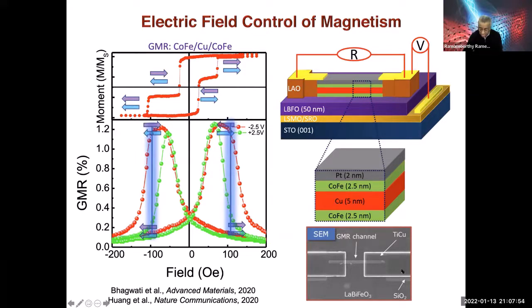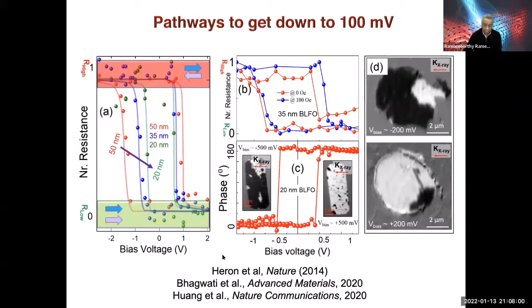Our colleagues at Intel fabricated 100 nanometer kind of devices. They all look essentially the same. The first challenge was how to go from 5 volts or 7 volts down to 100 millivolts. That's what Intel was asking for. So the first thing we did was to reduce the thickness. And this fellow who's now back at Bangalore as a professor, and Yenlin Huang, who's now back in Taiwan at Jiaotong as a professor, they worked very hard.